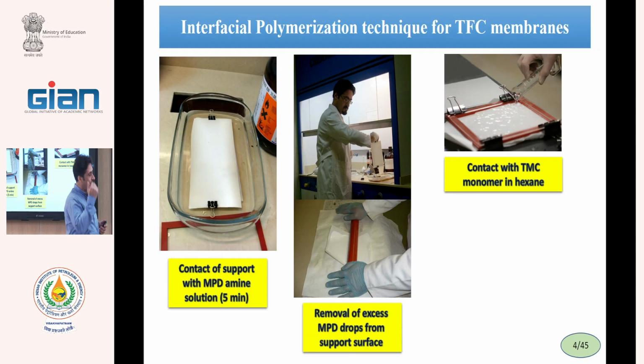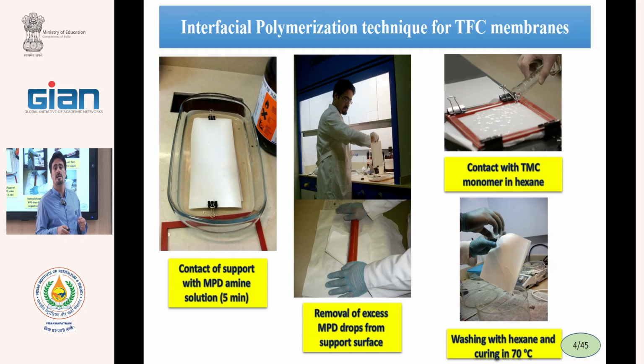The reaction is very rapid, complete in 2 seconds, but for completing, we usually give 30 seconds or 1 minute for complete polymerization. And next, the excess hexane is withdrawn and the membrane is washed with hexane for removing the unreacted monomers. Then we put this membrane in an oven for 10 minutes at 70 or 80 centigrade for completing the reaction. That is named curing. Curing means that we increase the temperature for completing the polymerization reaction.